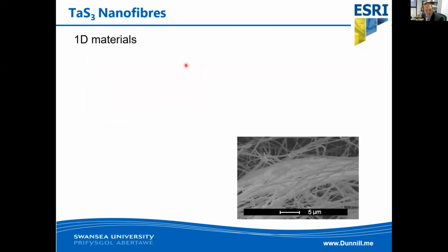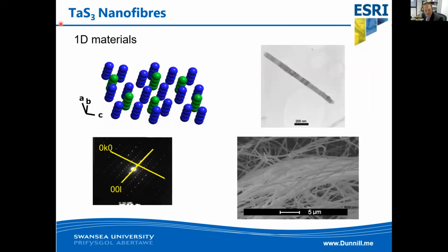What really gets quite interesting is when you start moving to TaS3, we're then in a position to form nanofibers of this very interesting one-dimensional material. What's really interesting about tantalum trisulfide is that we have these chains of green atoms that run through the structure, and they are the tantalum atoms. So we can look at making nanofibers that are effectively self-insulating wires with the tantalum atoms running down the lengths of the wires with the sulfurs around them on the side.